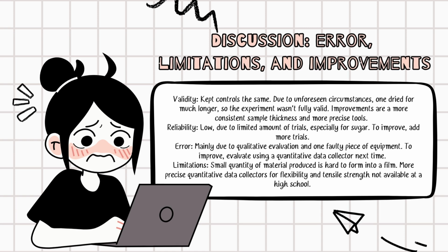Improvements could include having a more consistent sample thickness and more precise measuring tools, such as more precise scales. The reliability was also low due to the limited number of trials, especially for sugar, which fell short of the recommended 3 per variable. Improvements here would simply involve adding more trials. Error largely came from the qualitative testing and one experiment which had a faulty scale, which caused a mistrial due to the ingredients being measured wrong.